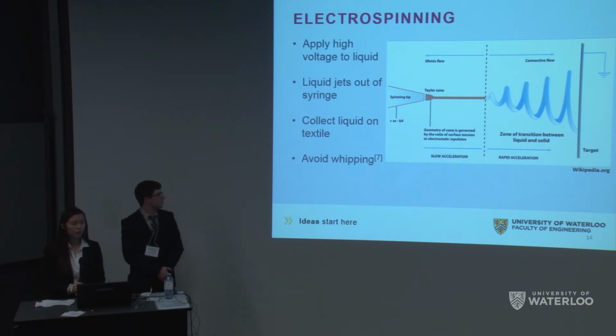So we had developed a fabrication method we wanted to use. The plan was to dissolve our zinc oxide nanowires in a solution of DMF and acetic acid in a 5:1 volume-to-volume ratio, and then heat it on a hot plate for 6 hours at 60 degrees Celsius in order to fully dissolve it. And then we would use a high voltage power supply in order to apply a potential to the liquid, which would allow us to electrospin it onto our cotton substrate.